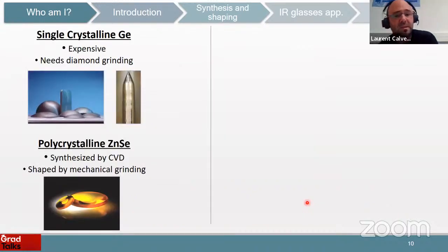So up to now, thermal cameras and everything working in the infrared use single crystalline germanium, as shown in these pictures. They are very, very expensive, and they need to be shaped by diamond grinding. They are synthesized by the Czochralski method. It takes a long time, over several months, to get this kind of germanium single crystal. Or you can also use zinc selenide, polycrystalline. It's made by chemical vapor deposition, so it's also a long process, very expensive. And at the end, you have to shape these lenses by mechanical grinding.